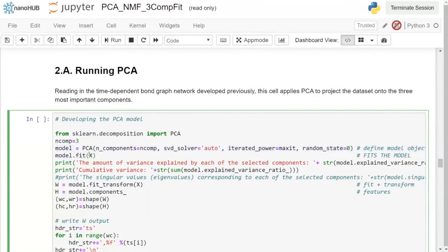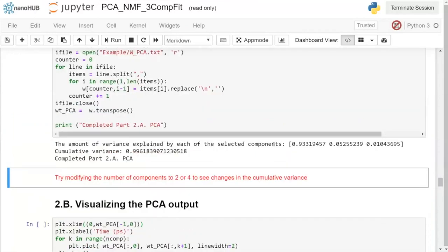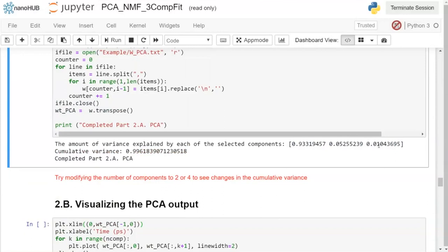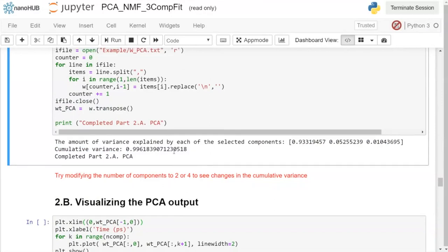We fit the model to our 280 bonding environments over time, then run fit_transform. With a three-component PCA fit, the first component explains 93.3% of all variance in the 280 features over time. The second component gives about 5%, the third about 1%, providing a cumulative variance of 99.6% — retaining almost all the variance with just three components.